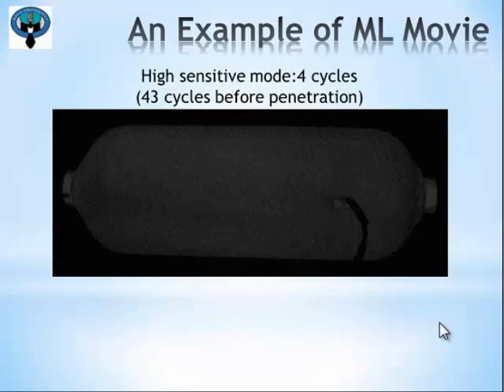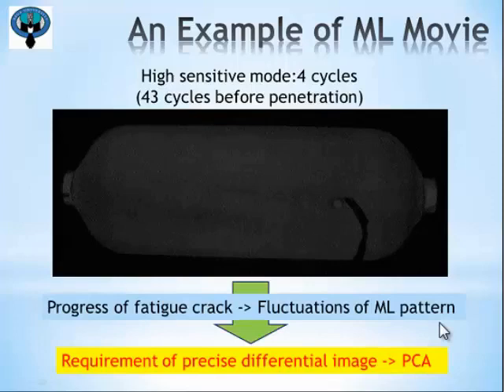After 43 pressurization cycles, a fatigue crack penetrates the liner. However, at a glance, we cannot identify the ML pattern produced by the fatigue crack. An important property of such pattern is to vary according to progress of fatigue cracks. Therefore, we should observe fluctuation of ML pattern. To avoid influences of various noise, precise differential images are required.